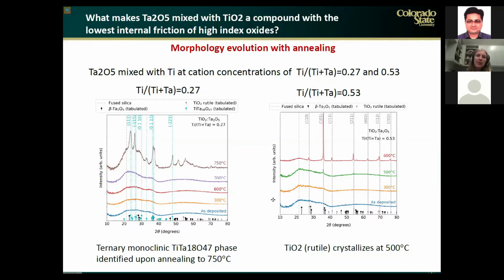So in this chart, what you see are results of X-ray diffraction that show the evolution of the morphology of the films with annealing. We studied 2 different cation concentrations. One that is 0.27, which is very close to the value of the cation concentration of the best tantalum titanium mixture used today, and another one that had a higher cation concentration of 0.53.